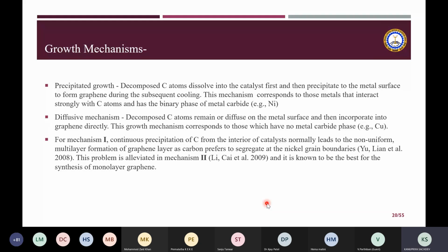If we use a substrate like copper, then the diffusive mechanism takes place, where the decomposed carbon atoms do not dissolve. They remain or diffuse on the metal surface and then incorporate into the graphene directly. When we compare the two mechanisms, the growth in the second case is more uniform compared to the first case, because in the first case there is a tendency of carbon segregating at the nickel grain boundaries, and that leads to a non-uniform multilayer formation. This problem is taken care of in mechanism 2, and that gives the best synthesis of monolayer graphene.